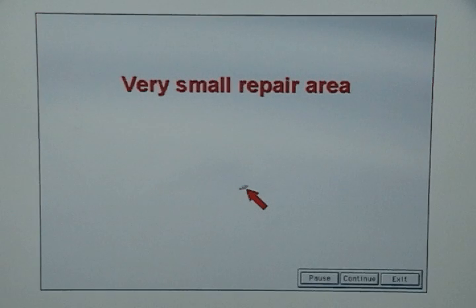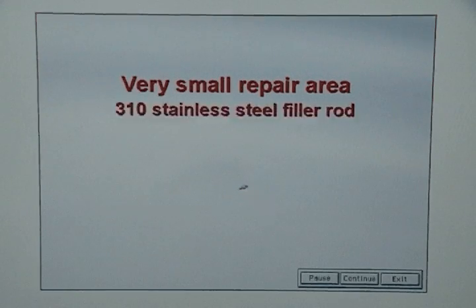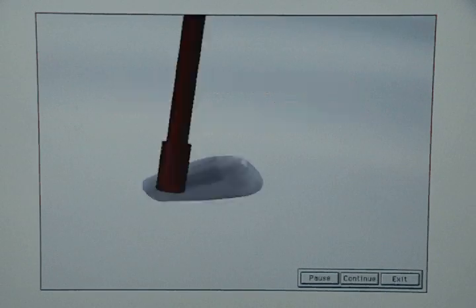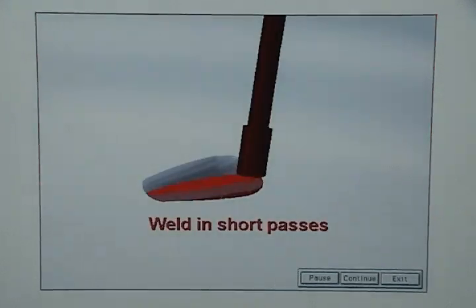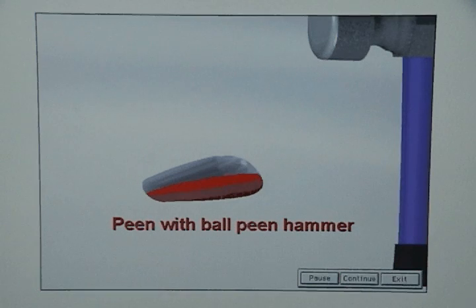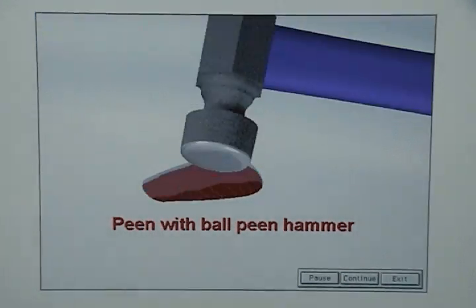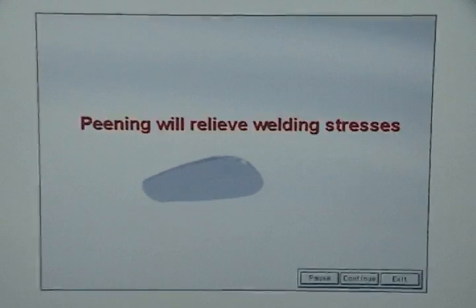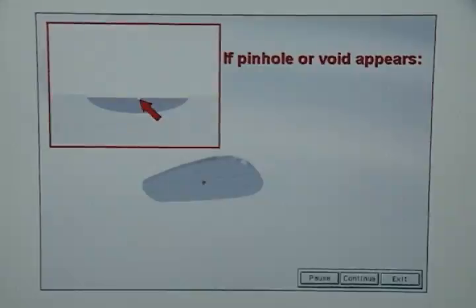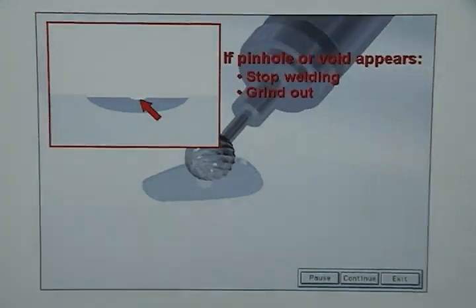If the repair area is very small, it can be welded using 310 stainless steel filler rod. However, you should remember that 310 stainless steel filler cannot be chromed. Be sure to create the weld using short passes and stop frequently to peen the weld with a ball peen hammer. Peening is a mechanical process of working the weld metal and will relieve welding stresses. Anytime a pinhole or void appears, you must stop welding, grind them out, and then resume welding.